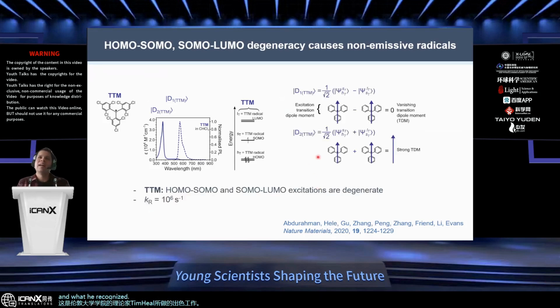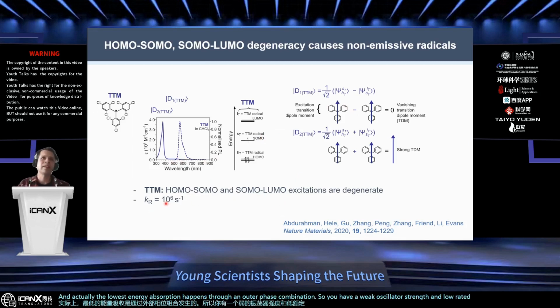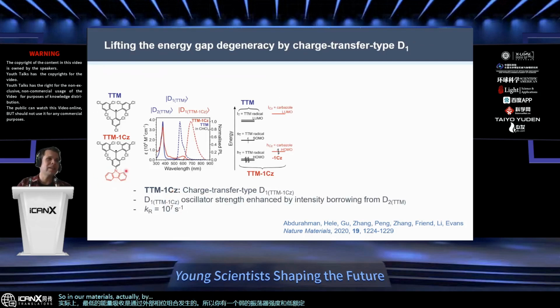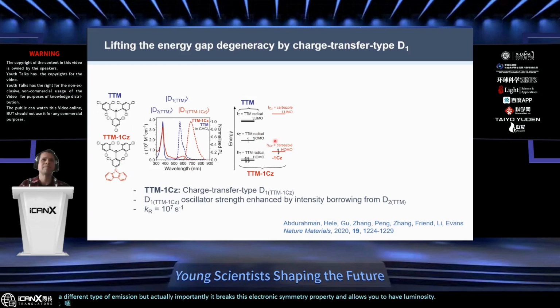And what he recognized by going through the quantum chemistry of this is that if you have this midway singly occupied molecular orbital, and I try to draw an electronic transition, that's the lowest excited state, I actually have to take combinations of HOMO to SOMO and SOMO to LUMO transitions. And actually, the lowest energy absorption happens through an out-of-phase combination. So you have a weak oscillator strength and low radiative rate. So in our materials, by employing this hole transporting material that creates this push-pull character, it not only creates a different type of emission, but importantly, it breaks this electronic symmetry property and allows you to have luminescent materials.